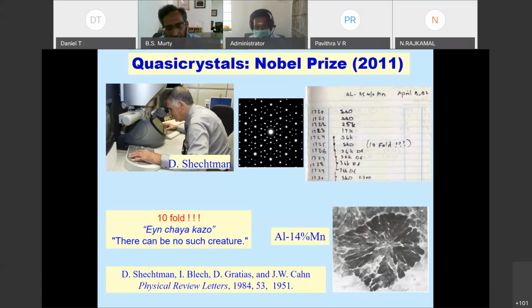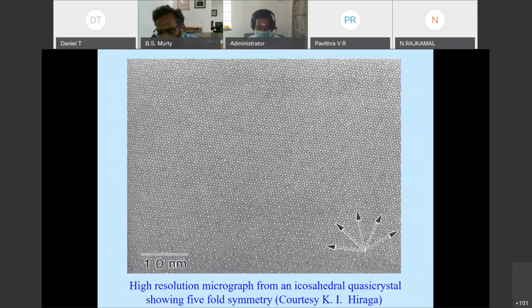And you can see here, this is an image taken from one such quasicrystal, where each white dot that you see is an atom. And if you carefully look at it, you will see a pentagonal symmetry and the tenfold symmetry that I am talking about inside the material.